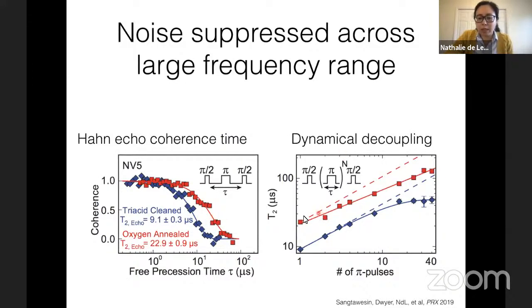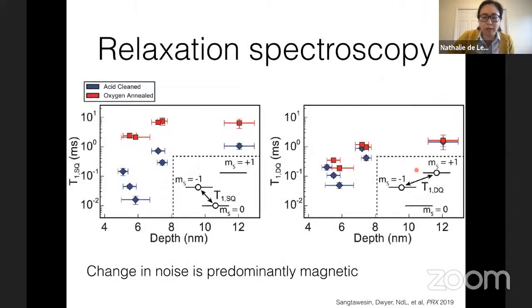And then importantly, if we do dynamical decoupling to probe what the noise looks like over higher frequencies, before you do this oxygen annealing, we see that as you increase the number of pulses, the T2 actually saturates. So you have this very broadband noise bath that you could not really just dynamically decouple your way out of. And then after you do this oxygen annealing, we see this kind of nice scaling with T2 where we're able to enhance the coherence time over a very large range.